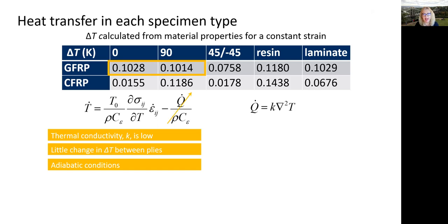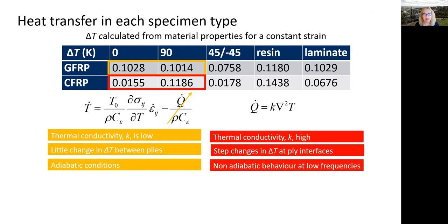On the other hand, we can see that with our CFRP material, the thermal conductivity of the carbon fiber is higher and there are step changes in delta T at the ply interfaces. So at low loading frequencies, the response is not going to be adiabatic.